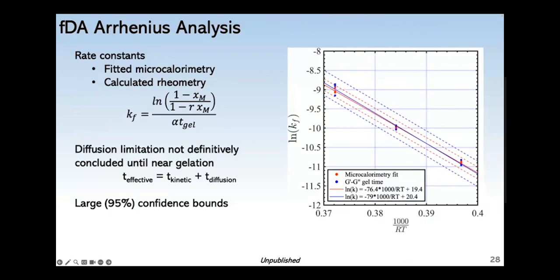So with the previous results now in mind, I was then able to fit the kinetic rate constants on an Arrhenius plot like the one shown here. So I have the natural log of the rate constant plotted against inverse temperature. So I obtained a set of rate constants from the microcalorimetric data, but I can also calculate a set of rate constants from the gel time in Flory-Stockmayer theory using this equation. So I show the fits for both. I have the microcalorimetry in red, and the rheometry gel times in blue.